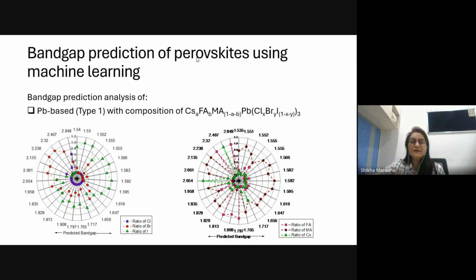This is one of the works that I did, in which the band gap reduction was done based on different compositions. One of the compositions was lead based, and this was cesium. The basis of this study was that I can change cesium, formamidinium, and methyl ammonium, and I can change their stoichiometric coefficients also. The total combination value should be 1, but A and B can range from 0 to 1. Any value can be there. Similarly, lead was fixed, but for the halides, bromine and iodide, the stoichiometric coefficients were also not fixed.